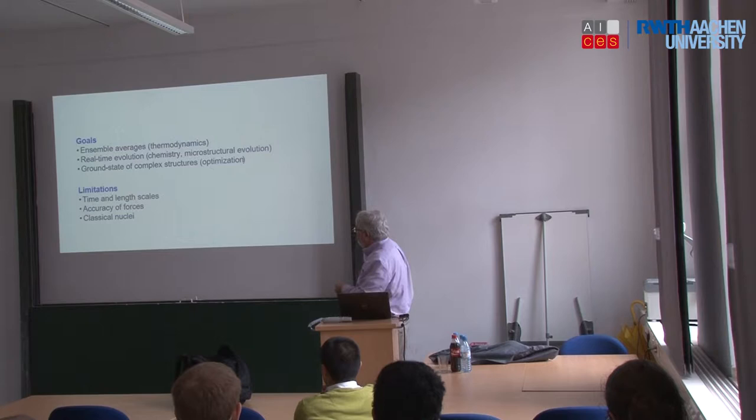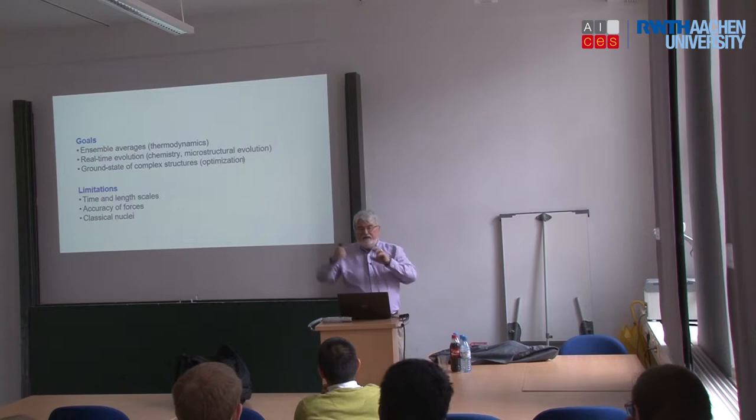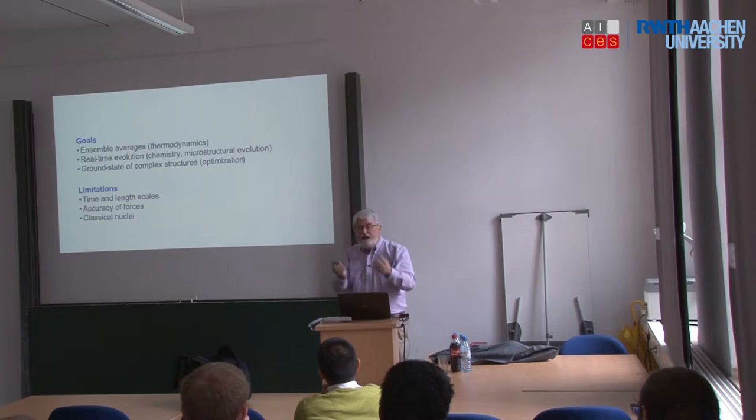We're not taking into account, we're not describing all the electrons in the system. We're just describing atoms basically as little balls interacting with each other and trying to write down an equation. That's the forces and the energy, which describes the effects of the electrons without including the electrons themselves. That's what makes it cheaper than doing electronic structure methods.